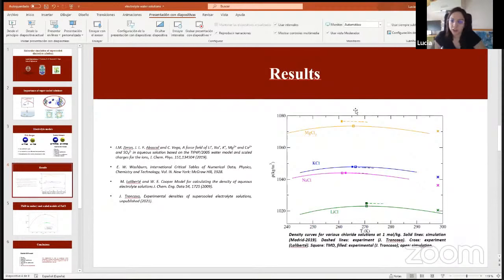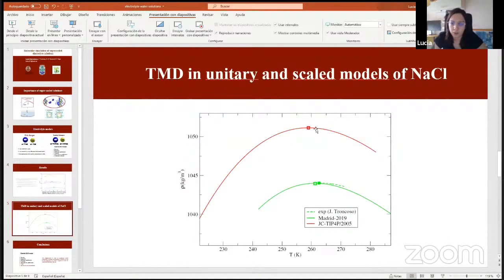And as we can see, the overall description of the Madrid 2019, which is represented by solid lines, is in very good agreement with the experimental data. And more importantly, the description of the density is not worsened at low temperatures with respect to ambient temperatures, as most of the models using unit charges do. Finally, we have also done molecular dynamics using the Joung-Cheatham model, which is one of the most used models with unit charges. And as we can see, it overestimates the density of the solution and underestimates a little bit the temperature of this maximum, whereas the Madrid 2019 model is able to reproduce quantitatively both the maximum and the temperature at which it happens.